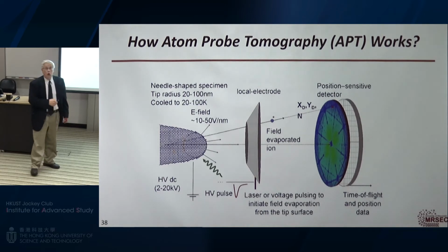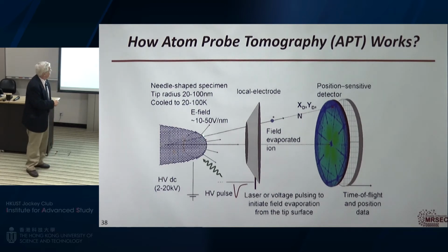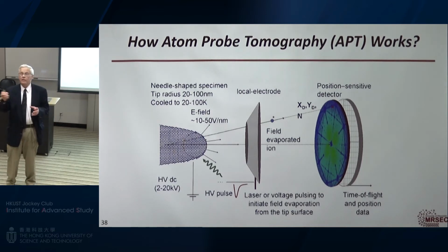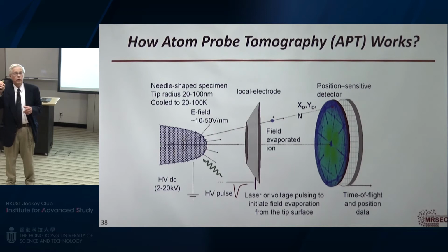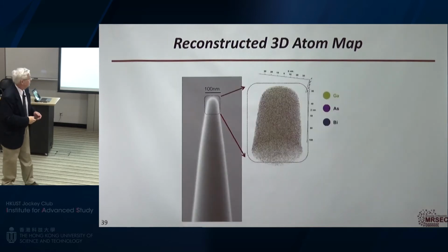So I can calculate the time it takes to go from here to here. That time will depend on the mass of the atom, so I can tell what atom that is. I can tell if it's an arsenic atom or a gallium atom. Since it's following a field line and I know where that is, where it hits this detector tells me where it came from in the sample. So I'm pulling the atoms off one by one. I know which atom I'm pulling off and where it came from.